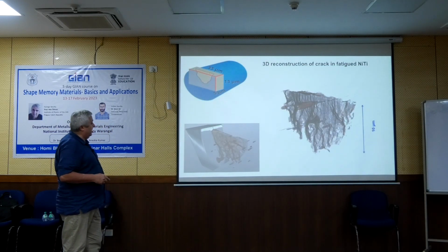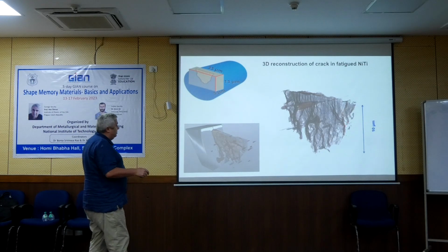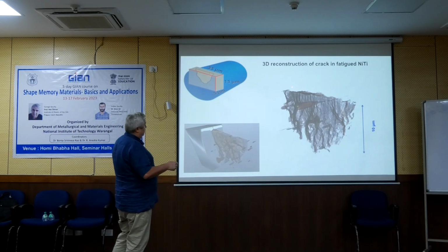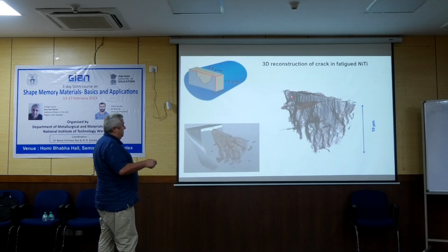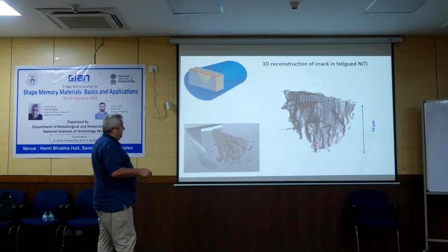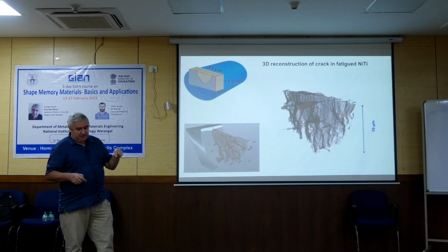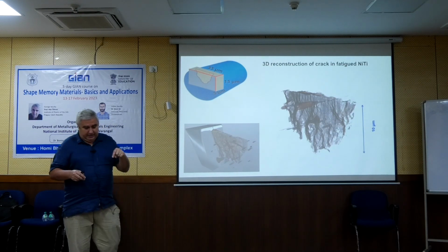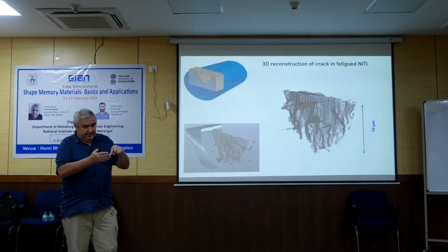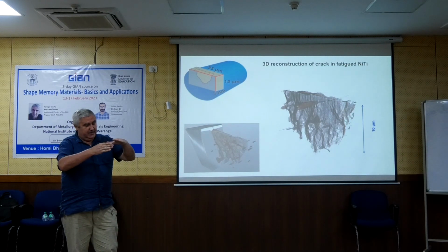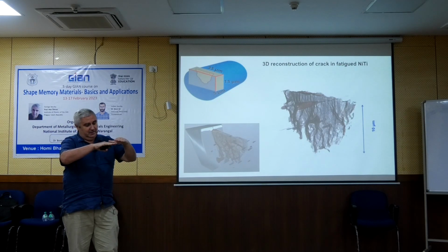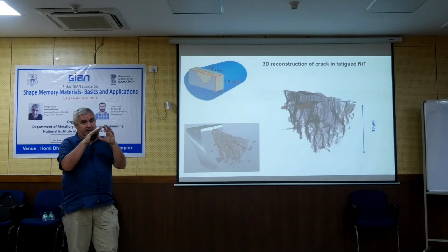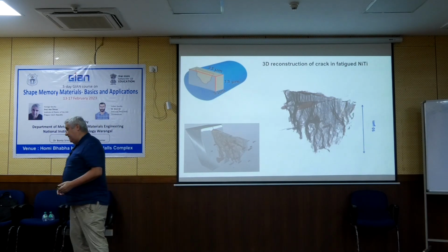At the time we bought our first SEM microscope equipped with FIB column, and with this, if you have a surface and crack, you can do such analysis that by FIB milling, a layer of the surface is milled, and a picture is taken, and milled and taken, and you go down and you can reconstruct in 3D the micro crack.